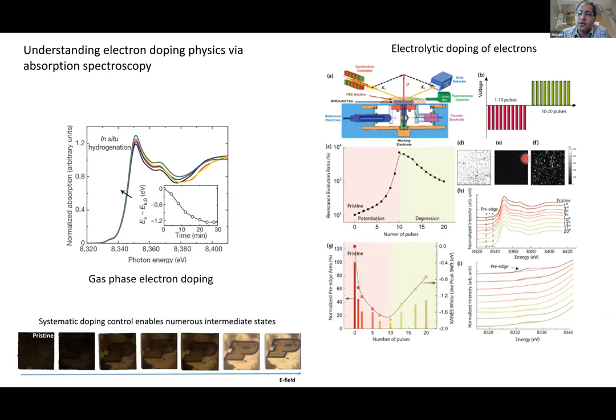And you can quantify this, and simultaneously you can do things like conducting AFM. So you can see here, this is mostly conducting, this is fully doped, and this is partially doped. You can see the electronic granularity that evolves. And in the long term, what we want to do is understand how the granularity relates to the global electrical resistance evolution. So that'll be fascinating. This is one of the early experiments we did with Dr. Huazhou many, many years back now, where we are looking at high temperature gas phase doping of these compounds. You can see this proof of concept showing that we could actually track the electron doping, and over the years we were able to do more careful in situ measurements.